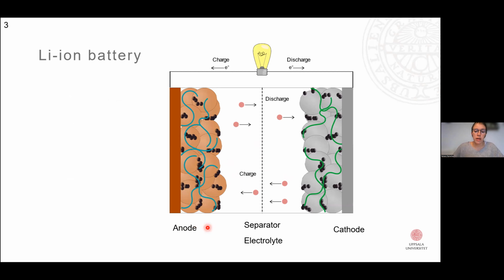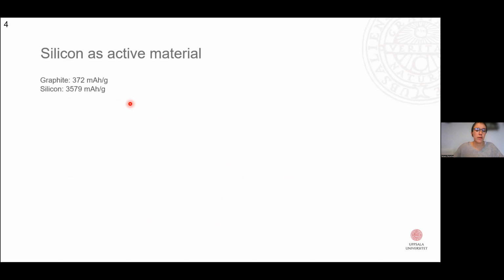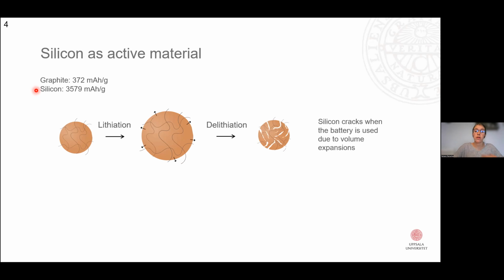So just to show you, in the lithium-ion battery, we will only focus on the active material that is silicon for the anode. So we are here. And if we compare the theoretical capacity for silicon to graphite, which is the current use of the anode, it's almost 10 times as high. But as you've seen before, there are issues with silicon. Otherwise, we would use this for the capacity already. So during lithiation, the silicon particles expand up to 300% of the original volume. And during delithiation, the material cracks, and this makes the material break down, and we are not able to utilize the capacity of it. So as a result, the capacity fades very rapidly.